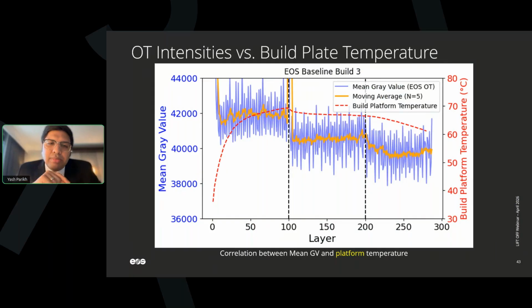When I start the build, on the right hand axis you can see the build platform temperature. It starts at about 38 degrees Celsius preheat temperature. This material is Ti64, by the way. So it nicely increases for the rectangular cross section. It becomes steady for my cylindrical cross section, and it nicely dips down again for my conical cross section. So this gets me to the fourth modality, which is the interlayer temperature and build platform temperature: it is in sync, and these signatures do correlate with each other. Go to the next one.